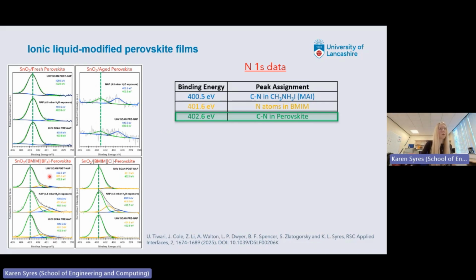But if we now look at the ones where we've mixed the perovskite with the ionic liquid, these are actually a week old. We made these at the same time as the aged perovskite and stored them in the same conditions. The only difference is that these have got the ionic liquid mixed in with the perovskite. And you can see that the ionic liquid has protected the perovskite from degradation. So you still got lots of this green peak that we want.